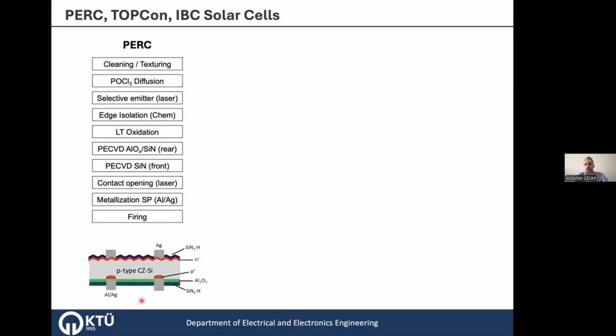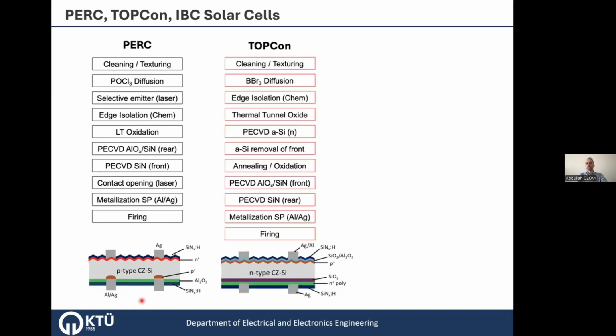So the TOPCon solar cell architecture, the TOPCon structure design, also uses the idea of PERC, a similar idea. In this case, we have a very thin silicon dioxide layer, which is 1 or 2 nanometers, and highly doped polysilicon on the backside to make the barrier, I will show in the next slide, and the anti-reflection and passivation on the backside. And we have silver contacts on the front surface.